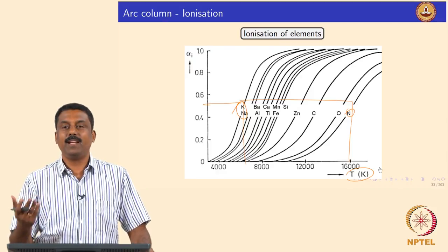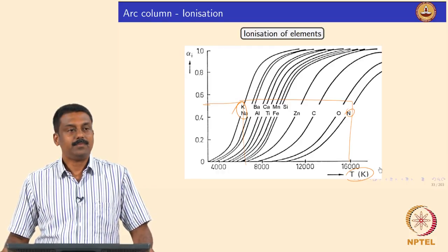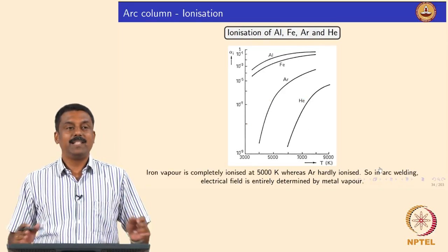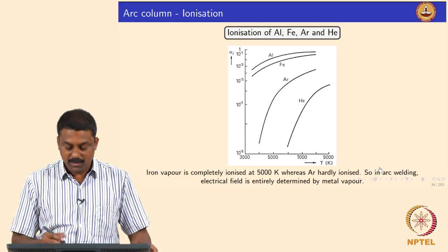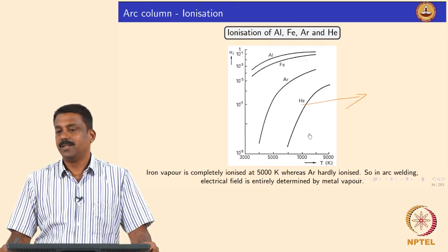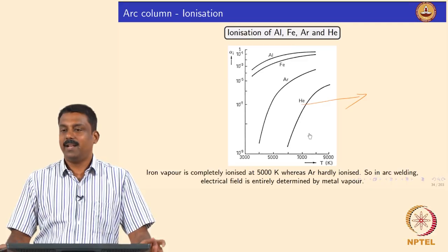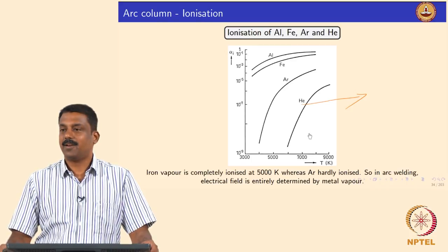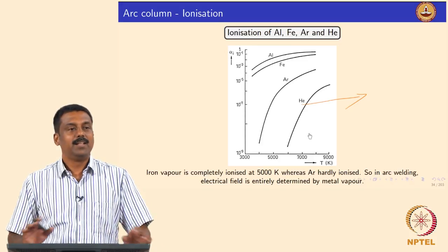You can choose whatever shielding gas you want, but obviously you will also change the arc temperature. Before looking at the shielding gas further — the moment you strike an arc using a shielding gas, for example helium, you have a tungsten electrode which supplies energy for initial ionization. Thermionic emission is happening; electrons are released from the cathode and they are going to the arc column.